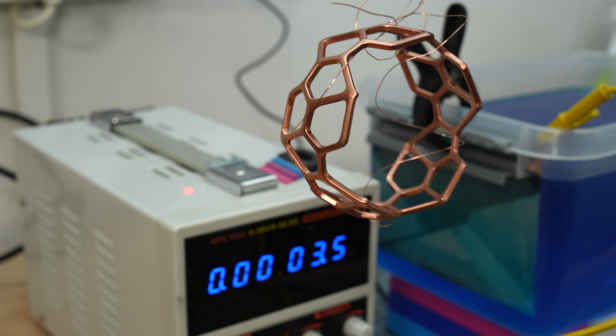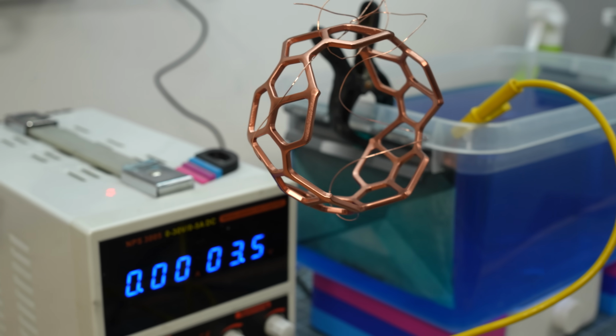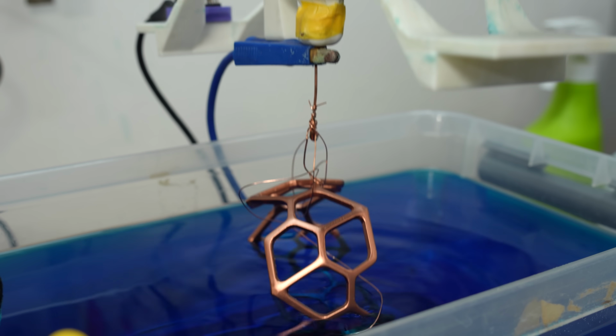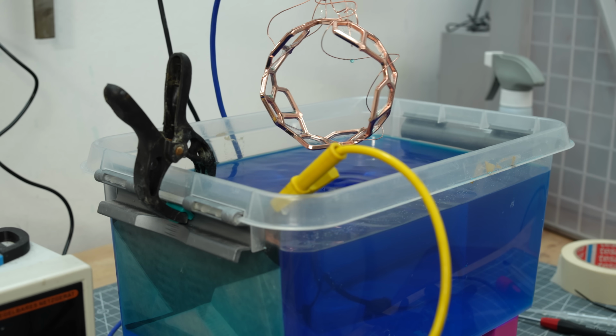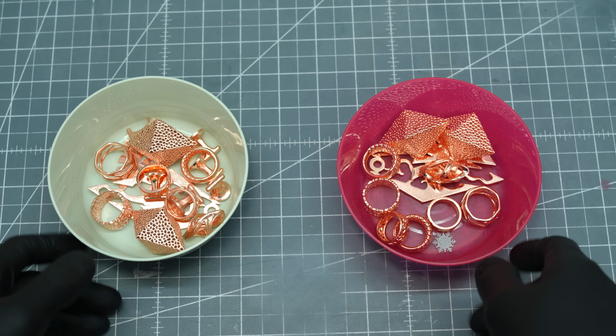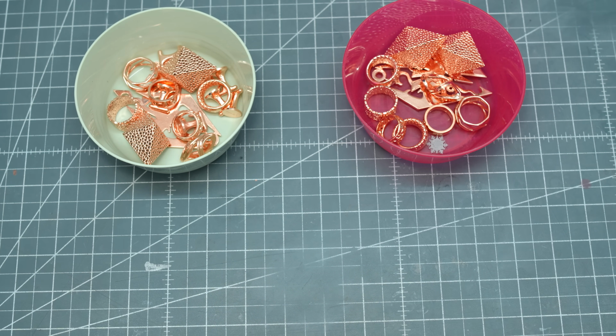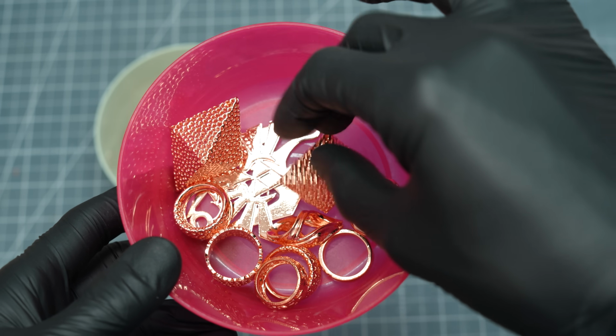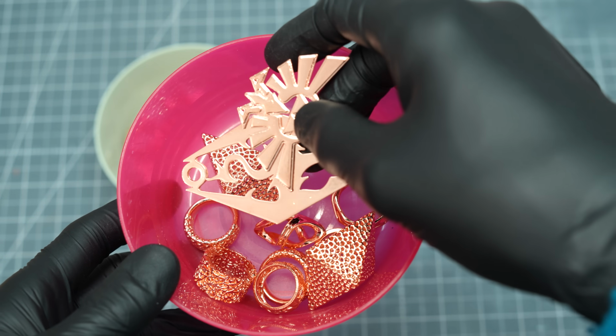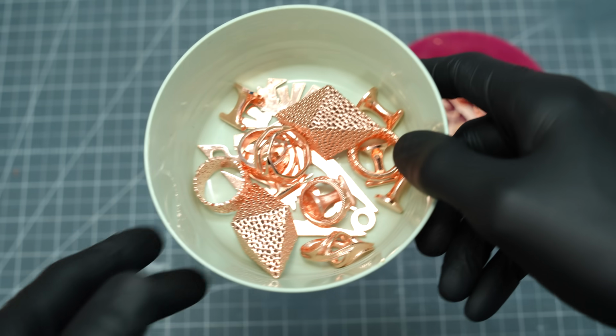Larger prints work very well too. In the end, you get shiny 3D prints coated with 0.2 millimeters of copper. That's relatively thick. There's no noticeable difference between the graphite and copper conductive paint.